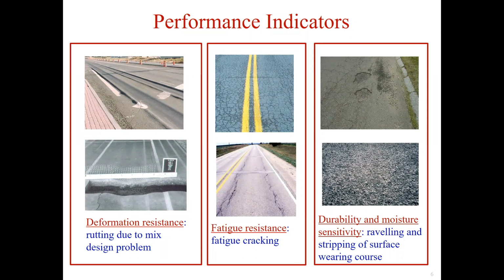There is also fatigue cracking due to insufficient fatigue resistance. By the way, fatigue is the weakening of a material caused by cyclic loading that results in progressive and localized structural damage and the growth of cracks. The fatigue behavior of an asphalt layer depends not only on the properties of the mix, but also on the structural properties of the underlying pavement layers, the traffic, and climate conditions.